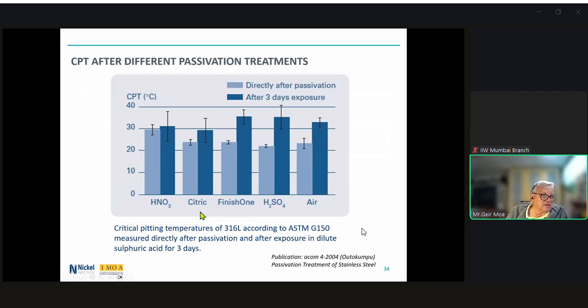The effectiveness of the various passivation treatments directly after pickling is assessed by determining the critical pitting temperature, or CPT, of the stainless steel. Directly after passivation with nitric acid, the CPT value is the highest, in comparison to the citric, Finish 1, the dilute sulfuric acid, and air. Then all the samples were exposed to a dilute 0.5% sulfuric acid solution for 3 days, and the CPT was measured again. After 3 days, the nitric acid CPT remained the same, and the CPT for the other methods were now at least equal to the CPT after passivation by nitric acid.